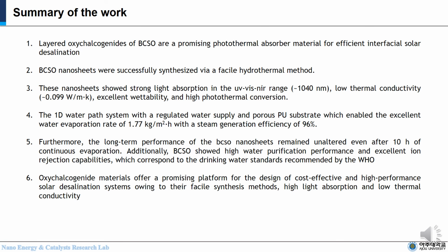Furthermore, the long-term performance of BCSO nanosheets remains unaltered even after 10 hours of continuous evaporation. Additionally, the BCSO showed high water purification performance and excellent ion rejection capabilities, which corresponds to the drinking water standards recommended by World Health Organization. Finally, the oxychalcogenide material offers a promising platform for the design of cost-effective and high-performance solar desalination systems owing to the facile synthesis method, high light absorption, and low thermal conductivity.